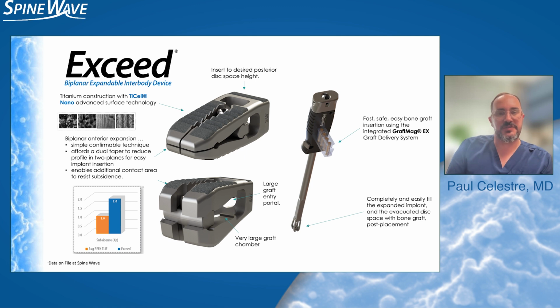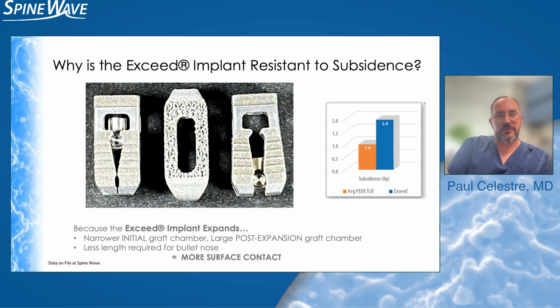As you can see, the surface technology is only on the superior and inferior sides, which allows smooth passage of the cage past the neurological elements. The roughness of the surface technology seems to help prevent against cage extrusion. One thing that I've noticed with the Exceed cage, as opposed to other expandable interbody devices, is a significantly lower incidence of subsidence. I honestly have not seen any of these cages subside into the end plates, even with very aggressive attempts at disk space expansion.